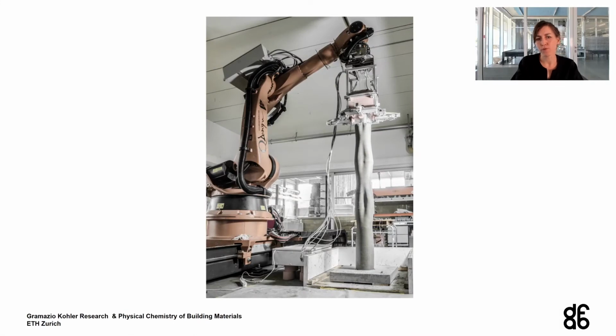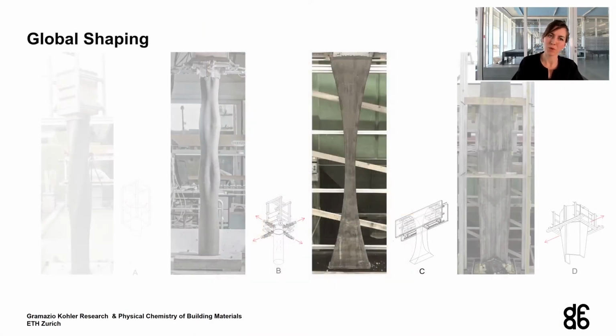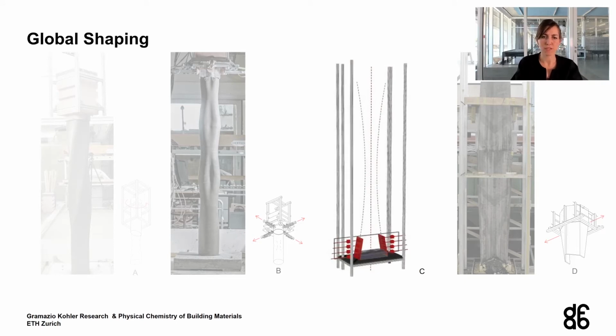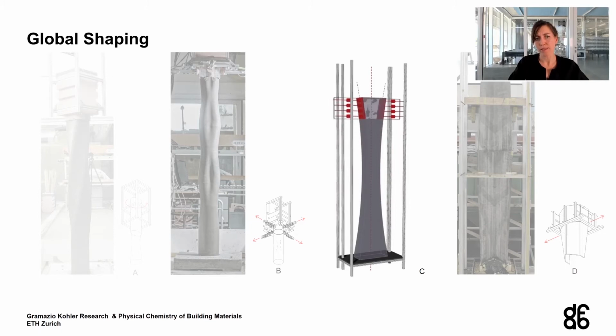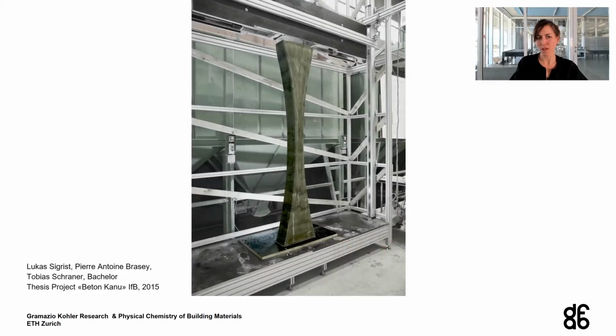So despite having a beautiful image with a beautiful column, we wanted to see if we could go a step further. Instead of only shaping at the very bottom of the formwork, we aimed to test shaping all around the formwork itself across the 40 centimeters, to disturb the material as little as possible inside of the formwork. This was very quickly successful, and we were able to produce a column which changed from 40 to 10 centimeters and back to 40 in a very short period of time within a bachelor thesis project at the ETH in Zurich.